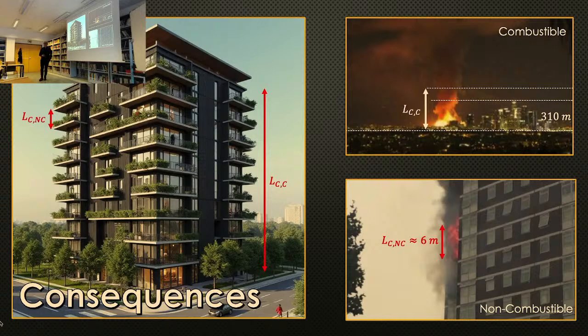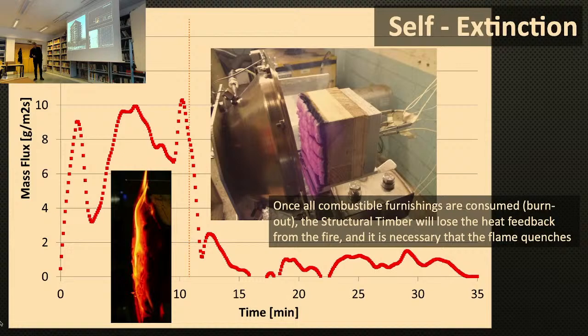So the consequences are potentially very severe, and therefore the reliance on self-extinction is really fundamental, and therefore we need to understand the process properly. So here's a very simple test by which you take a piece of timber. This is a CLT. This is a radiant heater, and you heat up the material. You allow it to ignite and burn. And you can see you have a burning rate of approximately 6 to 8 grams per meter square per second. And as soon as you take the heat flux out, you can see that the burning rate decreases and eventually disappears. You know, and this is the process of self-extinction.